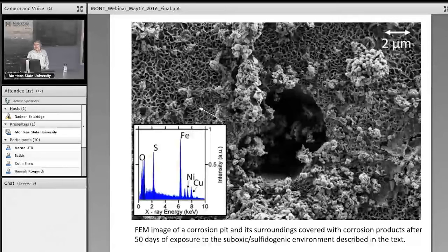Now you want to analyze what the heck is going on, what kind of materials they found. This is just the surface. We don't even know what's happening underneath this. So there are various multiple-phase approaches. We take an EDX spectra. That's your first line. If you don't know anything else to do, just go take an EDX. What you see here is iron, nickel, copper, sulfur, oxygen, standard things we expected.